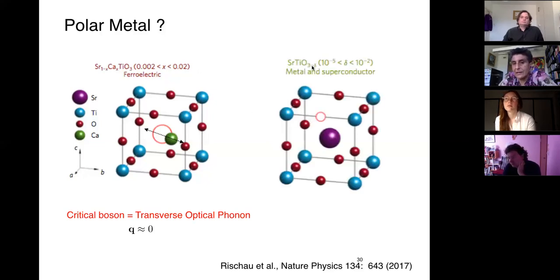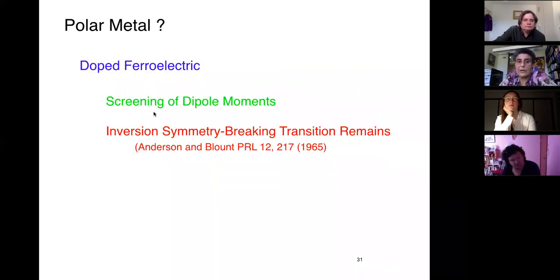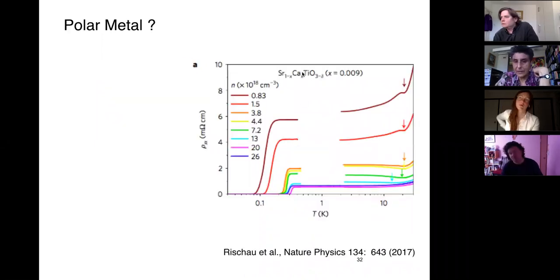But similarly, we also talked about the fact that if you take strontium titanate and deplete it, take away this oxygen, it can go metallic and eventually superconducting. And we talked about some of the challenges there. So what happens if you do both? What happens if you dope a ferroelectric? When you dope a ferroelectric, first of all, you're going to get screening of the dipole moments, so no polarization. However, the inversion symmetry-breaking transition remains, and this was actually pointed out early on in the work by Anderson and Blount. So that's exactly what Banya's group did. They took strontium titanate and added calcium to give it that critical polar mode, and then they depleted the oxygen. So here we have a polar metal.